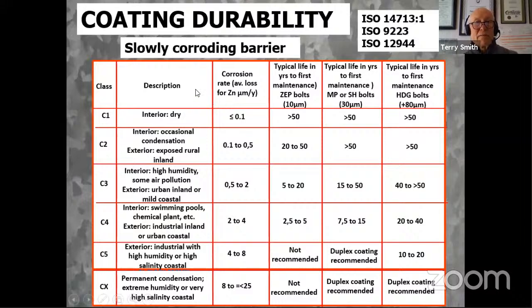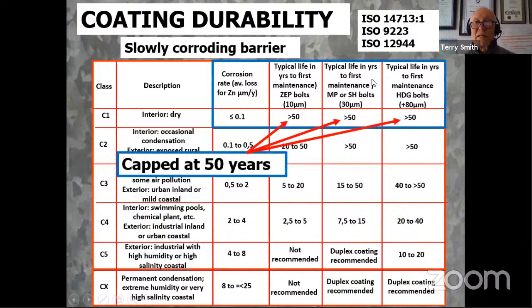The method by which galvanizing protects is a slowly corroding barrier, and you can see the 3 standards up here. ISO 9223 has distinctive classes of corrosion, C1 to C5 or CX, and we're just going to discuss the corrosion rate of zinc in microns per year in a C1 environment. Typical life of a zinc electroplated bolt, 10 microns, is 50 years. I've capped these at 50 years.